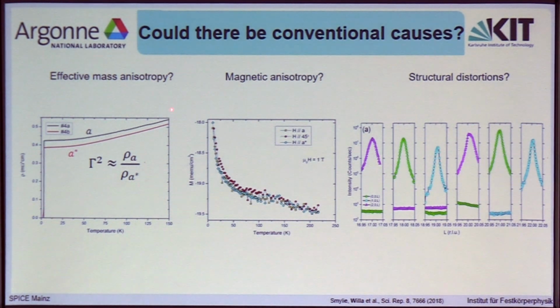A second thing that you could think is that there could be some magnetic anisotropy in the sample. So we've done susceptibility measurements, which also show no difference for different crystallographic directions. And the third option, that there could be structural distortions already present in the crystal. We've done X-ray diffraction measurements at room temperature, which do not show any deviation from the trigonal crystal structure. You can see here the Bragg peaks at the positions where they should be expected.